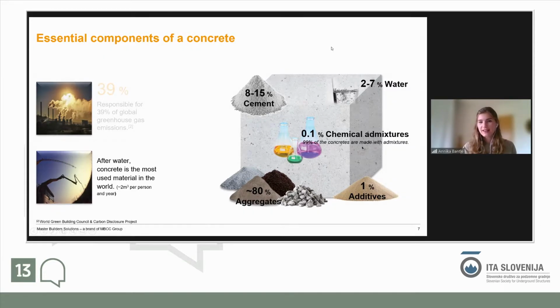So this is why I want to show you this little picture that I prepared. This is basically a cubic meter of concrete, and we have the contents. Basically 8 to 15% cement, which is of course for a very normal ready mix type of concrete. We have 2 to 7% of water. We have our chemical admixtures, which are dosed quite low. Then we have our aggregates, of course, and the additives.